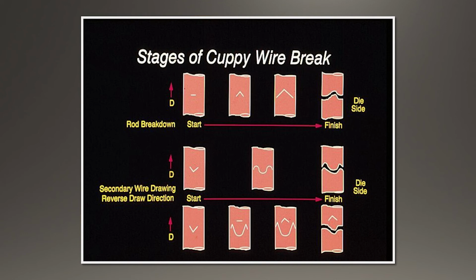And the crack will continue to grow, get bigger and bigger. And maybe if it occurred late in the process, you will get a wire break in a rod breakdown machine, and the cone end would be pointing in the direction of wire drawing. Now, supposing this is the process wire as it exited the rod breakdown machine. You can see it hasn't broke, but there's a defect in it.